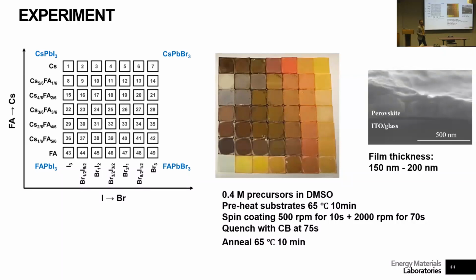And FA is right now a better choice than MA? Yes, because MA is 1 carbon, 1 nitrogen. It splits up at around 100 degrees, and then you destroy your structure. FA splits up at 200 and something. So the thermal stability of FA is much higher than that of MA.